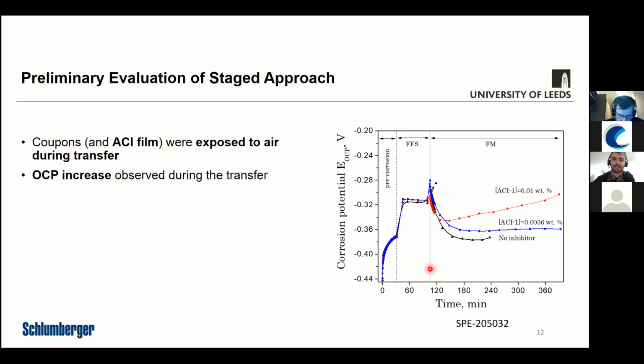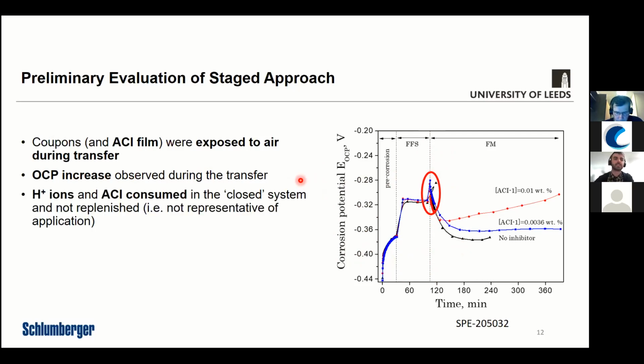During those experiments, the open circuit potential was tracked, and of particular concern was this sort of spike here in the OCP. So this is as the coupon was transferred between the beakers. That was a particular concern because that, again, implied that some sort of uncertainty or error was being introduced into the experiment. So in terms of the methodology, those were limitations.